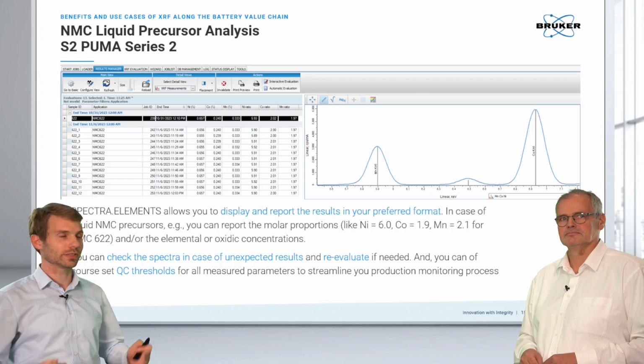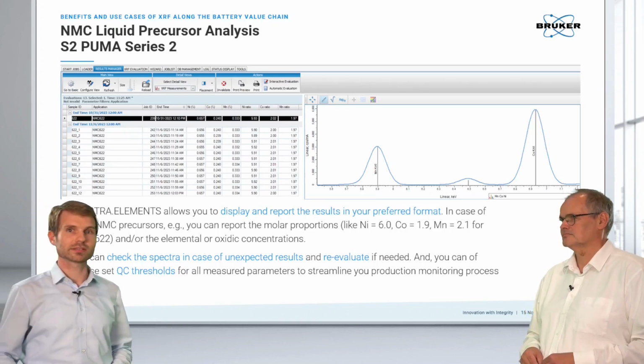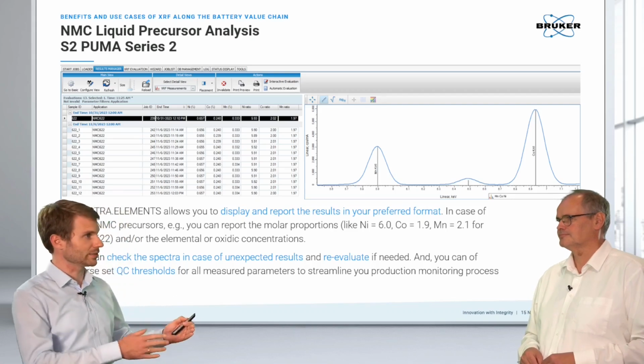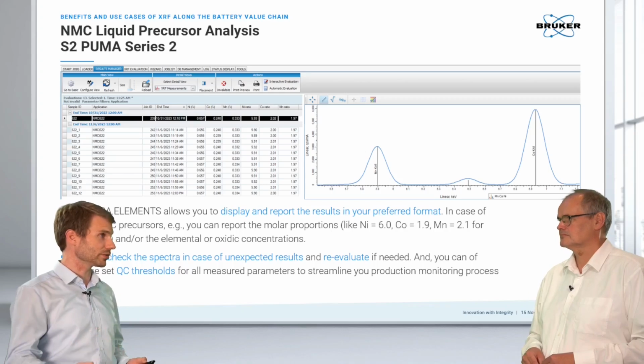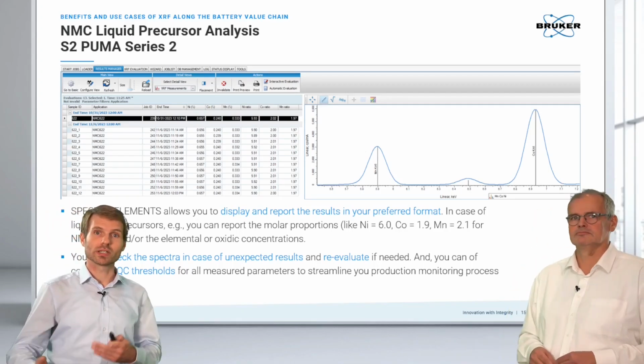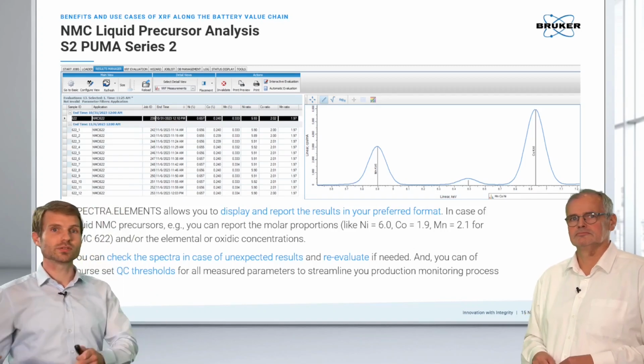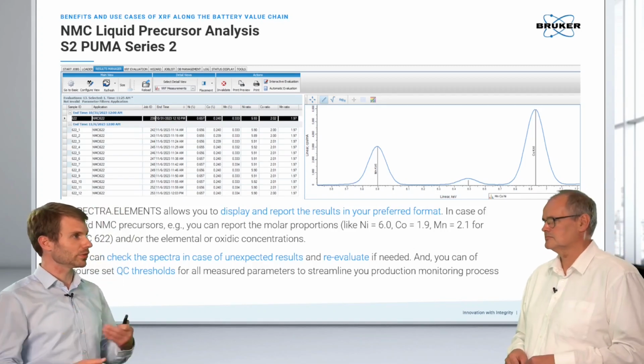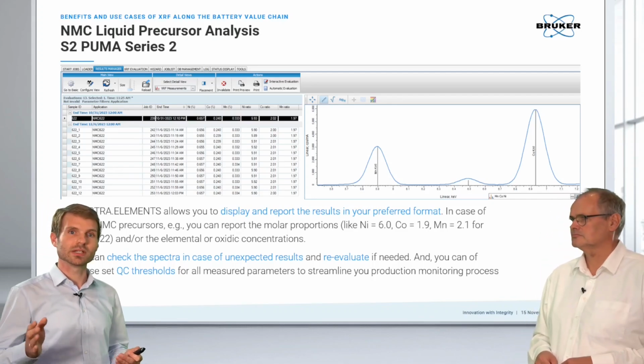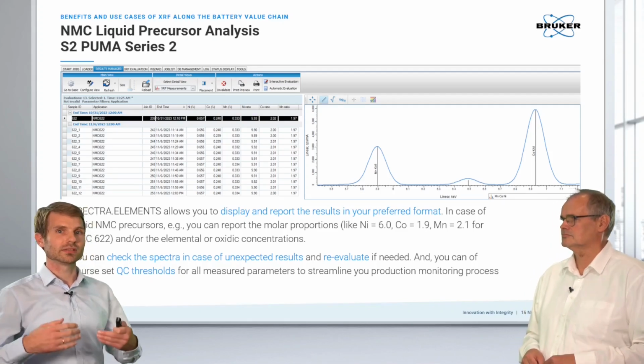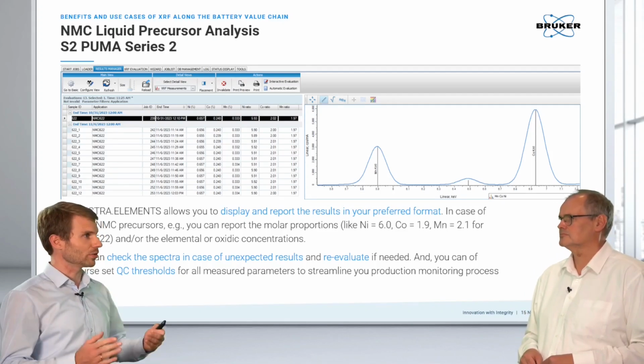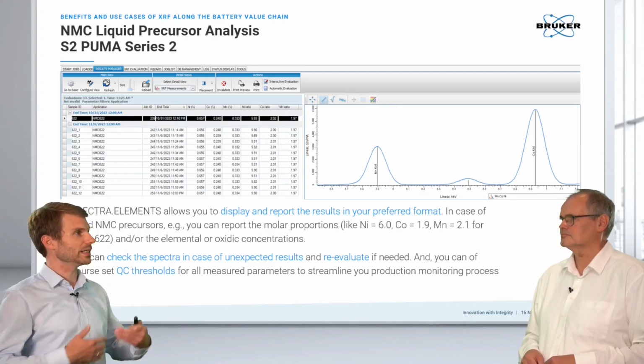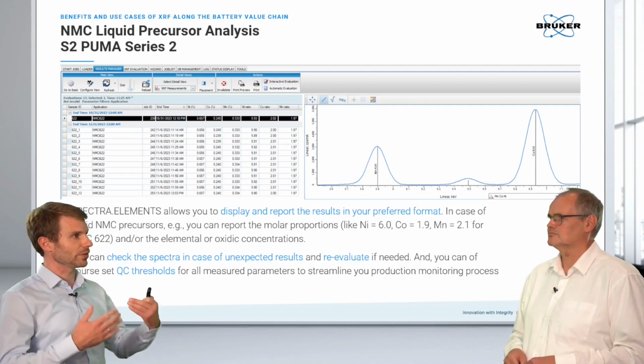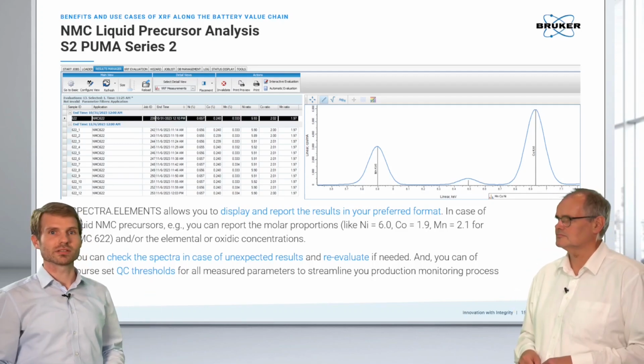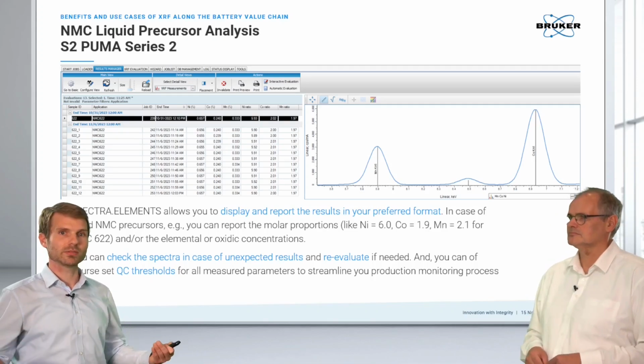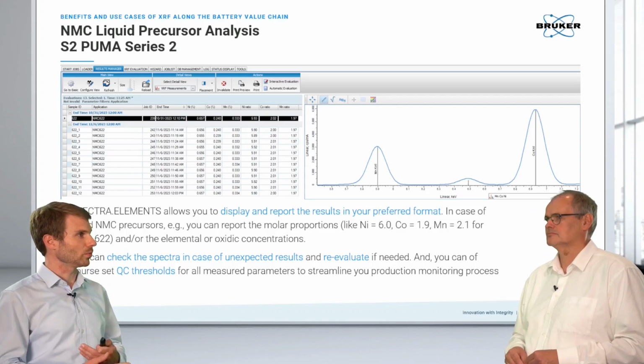There's a snapshot from our software, left-hand side. You see how the results can appear. Like Kai said, you can express that as concentrations, elemental concentrations, oxide concentrations, whatever you find more fitting. You can also transfer this into a more useful space for you, into the molar ratios according to the NMC type. So you can, for example, say you have a 6 to 2 to 2 type, and see how close you are. Based on that, you can determine thresholds. So for the operator, it's very easy to make a decision based on the threshold. If something red pops up, it means simply out of spec, we have to do something, whatever our standard operating procedure defines.